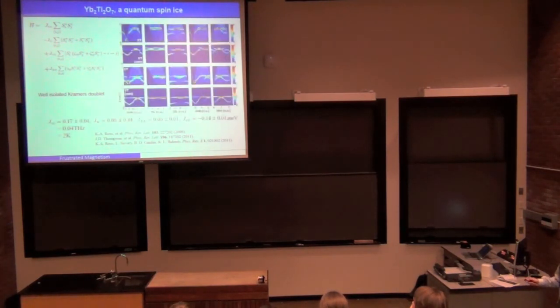And this is what people have done with neutron scattering, shown here. And here is the data, this dispersion of the spin waves they collected at 5 Tesla and 2 Tesla. So these are in the field-induced order state. So you have well-defined spin wave dispersion. They collected the full spectrum of these spin waves, and they also did the theoretical fitting to those spin waves. As a result from the fitting, one is able to obtain the spin interaction parameters. The full Hamiltonian can be extracted, and these are the parameters obtained by fitting to the experiment data. So this panel and this panel are the experiment data, and this panel and this panel are the fitting from those parameters. You can see they agree very well.